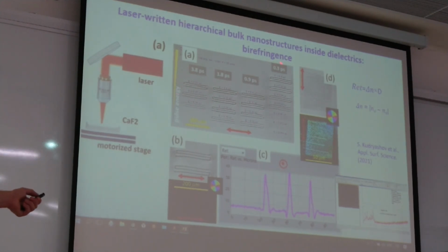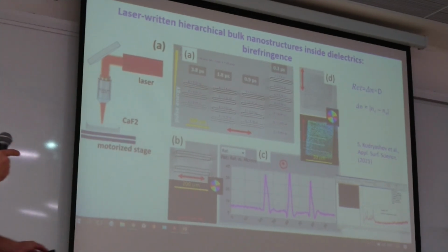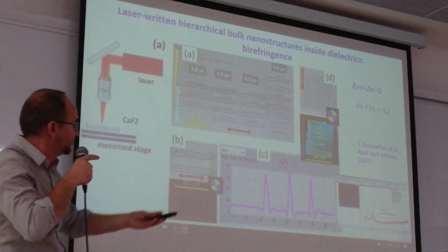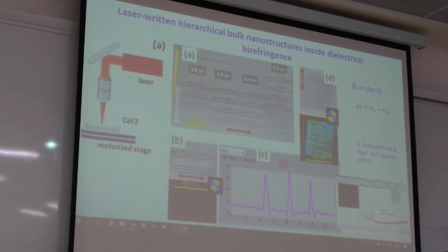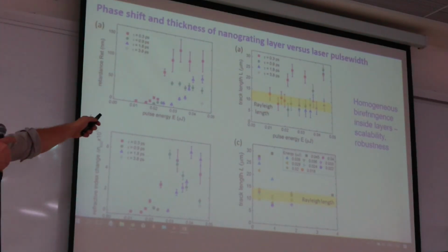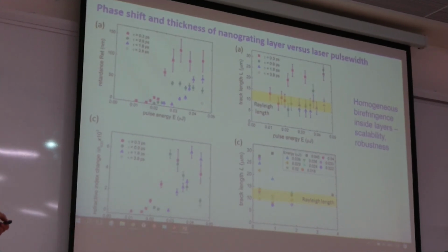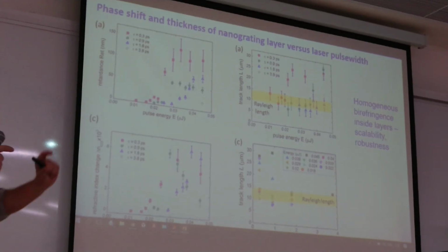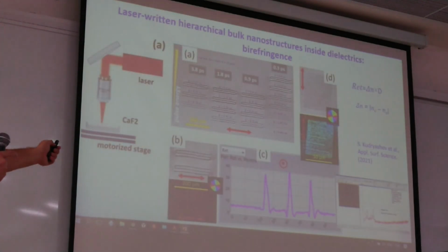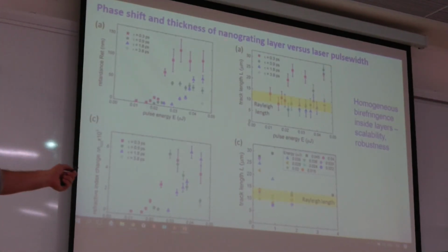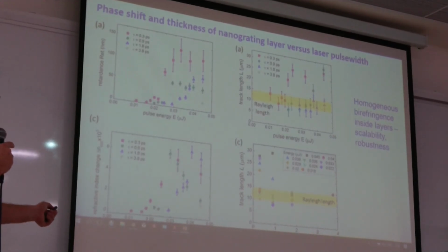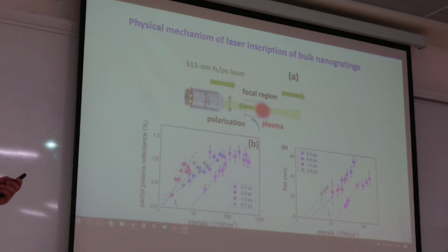We use different pulse widths and different energies to produce these kinds of tracks. And these tracks are showing birefringence in a polarizing microscope. So there is a difference in refractive index between the ordinary and extraordinary wave. Okay, and we can see, as a function of energy, this phase shift, and we can see the thickness of the region modified by the laser, and dividing the phase shift by length, we can calculate the change of refractive index, and it is about 10 to the minus 3, and it's good to produce different optics. Probably I skipped the physical.